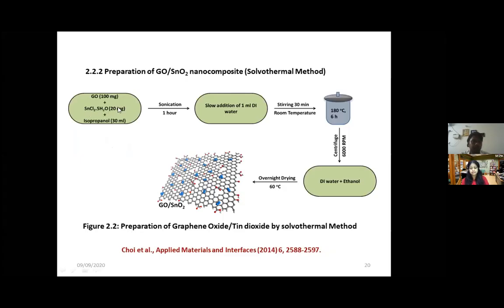Tin dichloride pentahydrate is the precursor for the formation of tin dioxide. We have taken a 5:1 stoichiometric ratio. This study has found that 5:1 of graphene oxide and metal oxide would provide selective detection of acetone, so we use the same stoichiometric ratio. It is called the solvothermal method since we use a solvent, isopropanol, 30 ml, sonicated for 1 hour. In the presence of isopropanol, if we sonicate the nucleated graphene oxide and this tin dioxide precursor, we obtain a dispersed solution.